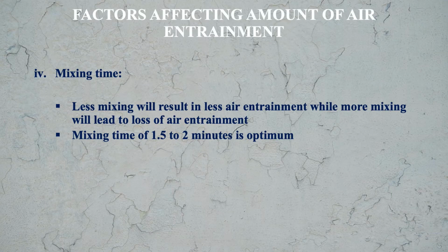So what is the optimum mixing time? Optimum mixing time is taken as 1.5 to 2 minutes, means 1.5 minutes to 2 minutes is taken as the optimum time for mixing of the concrete.